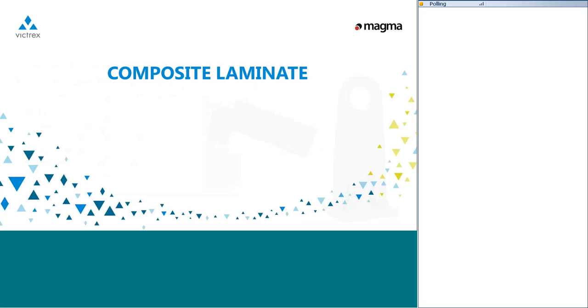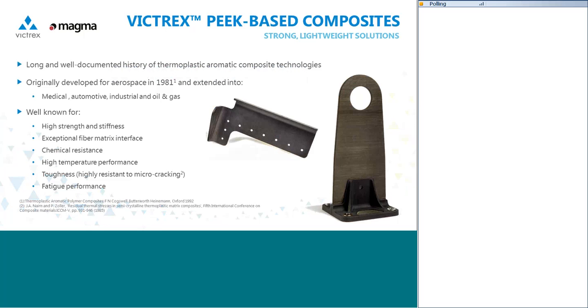Now, moving on to the composite laminate. As with the PEEK polymer, PEEK-based composites have a very long and extremely well documented history. I think, to be honest, that PEEK is probably one of the most documented composites in the whole of the materials world. It was developed back in 1981, mainly as an aerospace material, but since then it's been extended into medical applications, things like trauma plates, which require very high fatigue resistance, loaded brackets for, as you can see in this picture, aircraft parts, which are again critical parts and need very high fatigue resistance. And in the energy industry, there are already applications in areas such as wear rings and compressor parts.